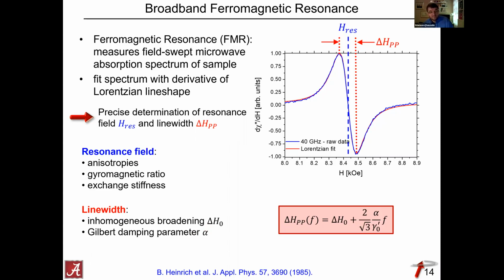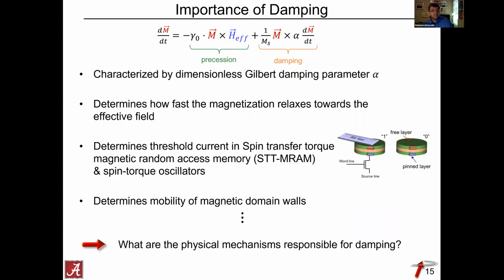Now the equation that links the peak-to-peak line widths with these interesting parameters is given here, and it's a simple linear relationship. So what that tells you is, the gyromagnetic ratio you can determine from the resonance position. So the only free parameter here is your damping parameter alpha. So if you're able to measure the line widths over a broad frequency range, you should be able to very precisely determine the damping parameter of your sample. So that's kind of a little background. And obviously this damping parameter is immensely important for a number of things.